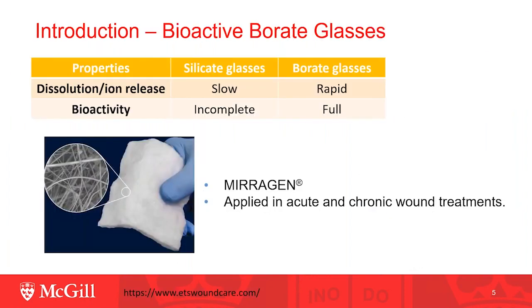However, silicate glasses have a slow dissolution rate and incomplete conversion to hydroxy carbonate apatite, which limits their wider application. Due to structural differences, borate glasses have lower chemical durability and higher dissolution and bioactivity than silicate glasses. Therefore, borate glasses have a greater advantage in mineral tissue regeneration and wound healing. One borate glass has obtained FDA clearance as a wound dressing. The properties of borate glasses are much dependent on their structure, so the structural features of borate glasses will be revealed first.